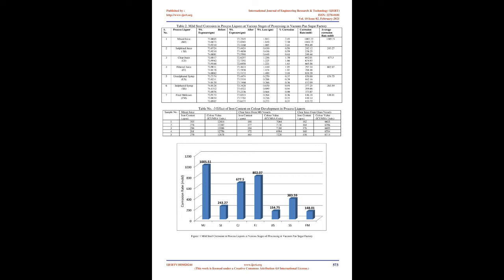Corrosion in final molasses. The data obtained with regard to mild steel corrosion in final molasses has been presented in Table 2. It can be observed from the table that corrosion rates in final molasses are considerably lower and comparable with those in unsulfured syrup. Such behavior may be attributed only to the higher total dissolved solid content, 85 to 87%, of the final molasses. It is accepted that at such a high dissolved solid concentration, the quantity of dissolved oxygen, which has a prominent role in corrosion, will be very low.